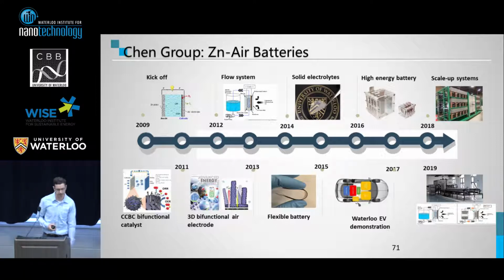So here our group has demonstrated, mainly on the air electrode side, materials which will allow you to both reduce oxygen during discharging the battery and then do the oxygen evolution reaction, which you need to charge the battery, and finding materials which can do both of those things well enough with a high efficiency and a good cycle life.